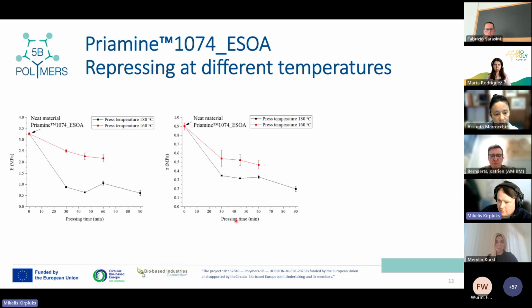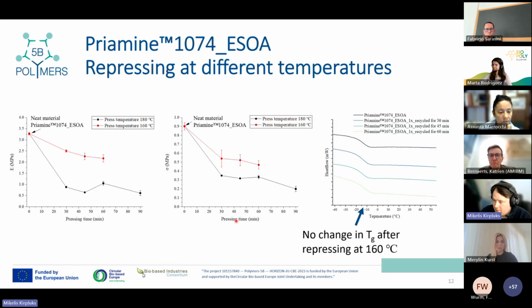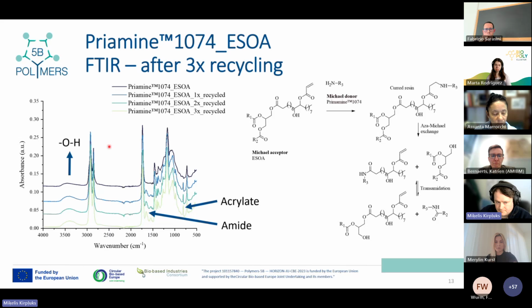The drop in the mechanical properties was not so visible if we reduced the repressing temperature, but still with every step we have a decrease in mechanical properties, which is not good. We tried to figure out what is happening there, and we think that we found the culprit. This is the epoxidized soybean oil acrylate component.